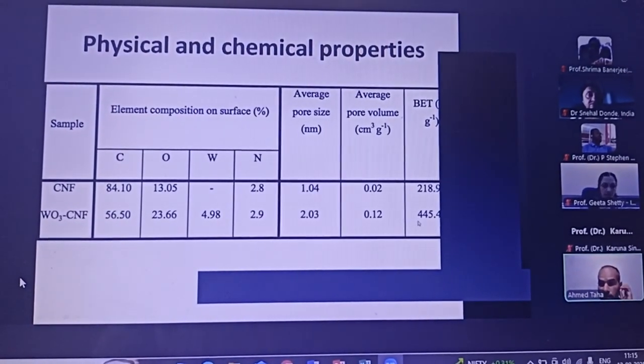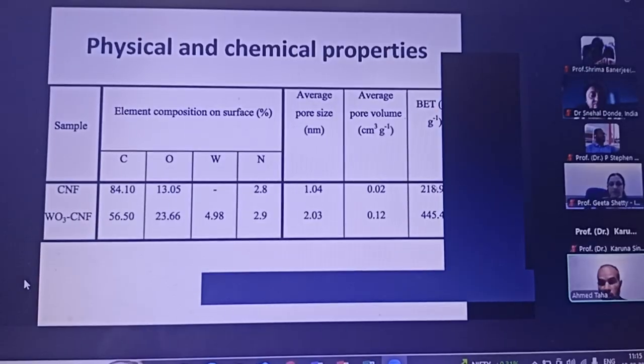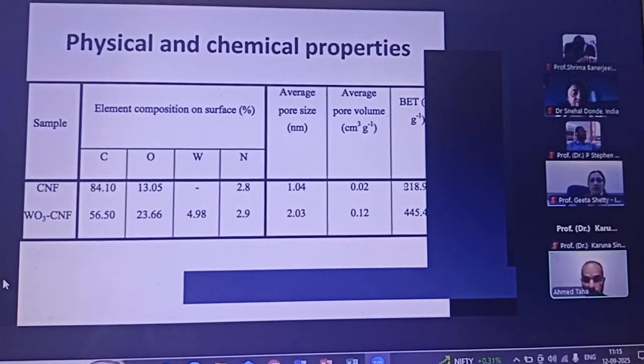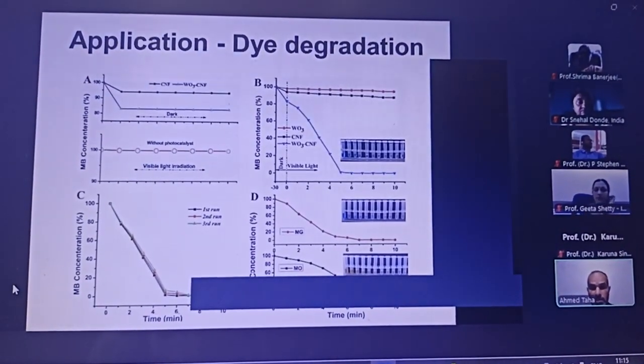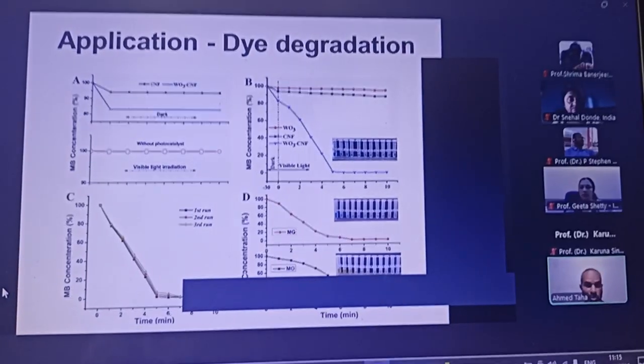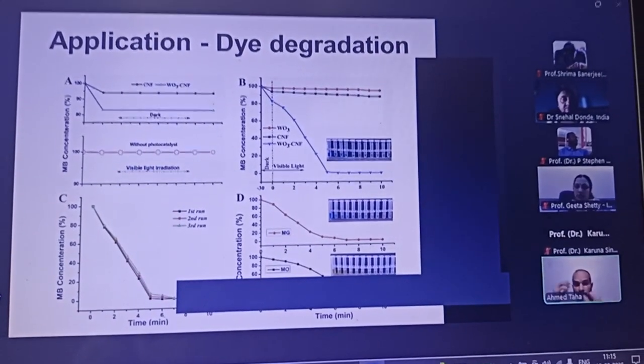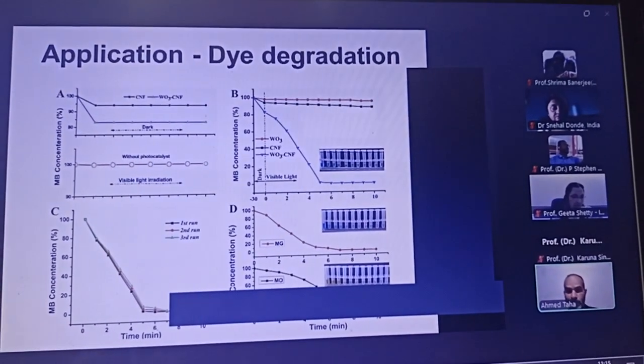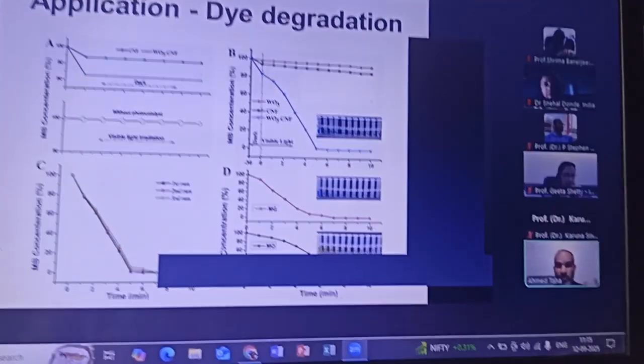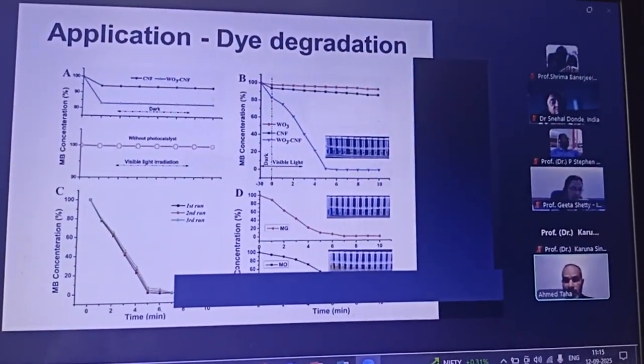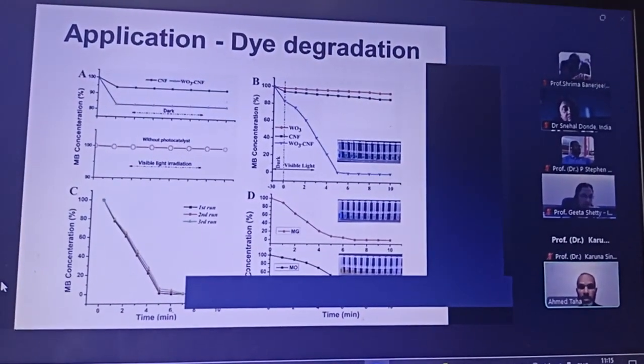The surface area was like double the surface area of the bare carbon nanofiber. And this is the application. So we took this fiber, mixed it with our organic pollutant. We use a dye, so we can see it by our eyes. We can easily detect it by the spectrophotometer.